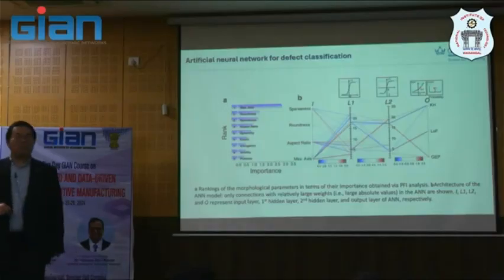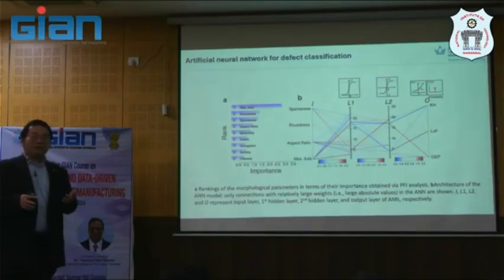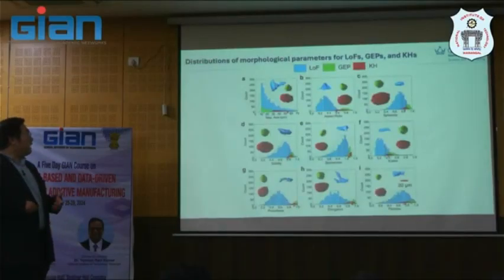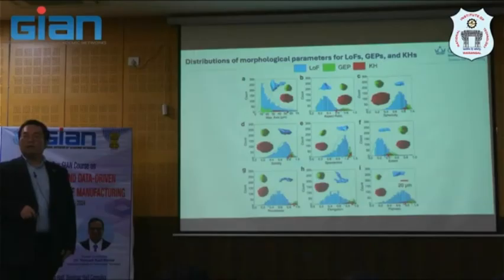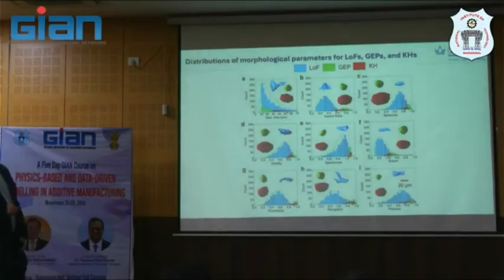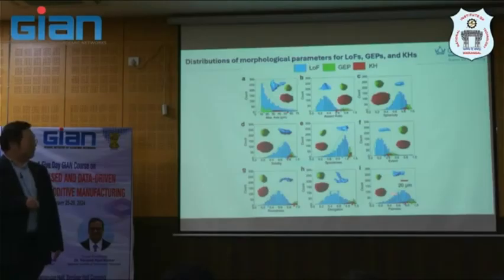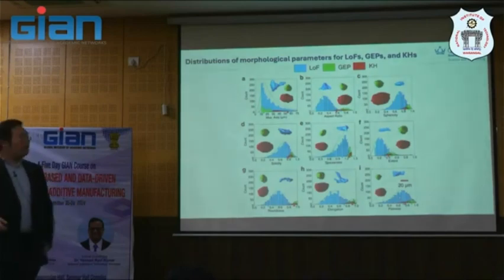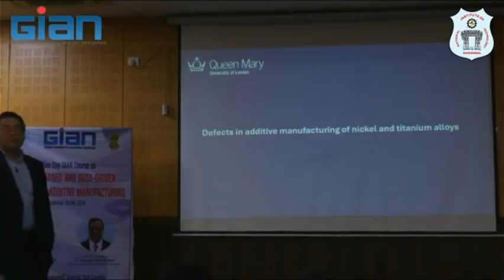This is the example I just want to show of how they classify the defect and how important this is. Because if we don't understand this characteristic, or if we can try to minimize this lack of fusion to a very minimum distribution, this is probably the goal that we want to control. But I don't think we can actually remove every porosity from your part; it's about understanding. You may not prefer this porosity profile for sure, but this one with a very minimum distribution, the maximum frequency here, minimum frequency here, may be acceptable for the application that we need. So I think this is quite a clever way to have this systematic classification by an artificial neural network.